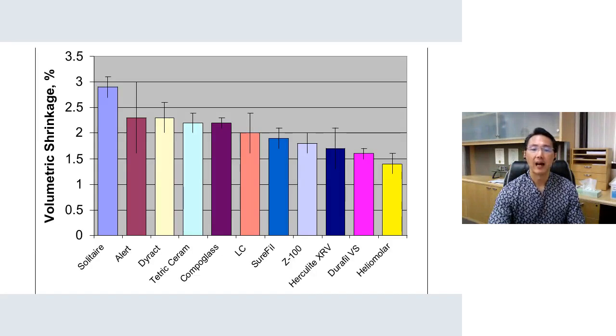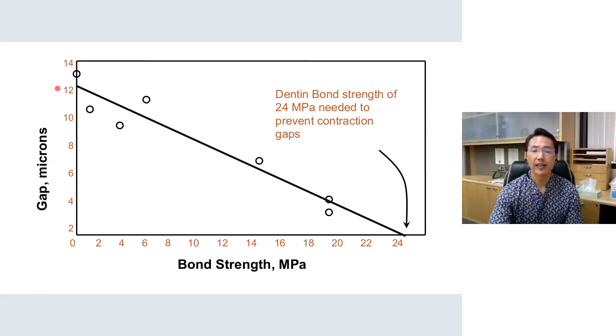This graph was created in one of our labs, and basically you'll see that these are different brands, and you can see the volumetric shrinkage, and Heliomolar actually surprisingly being fairly low, but this is kind of what they look like. 1.5 to about 3%. And this graph shows the gap that can form because of the bond strength. If you want no gap to form, you needed to have about 24 megapascals of bond strength to stop the shrinking composite from forming that gap.